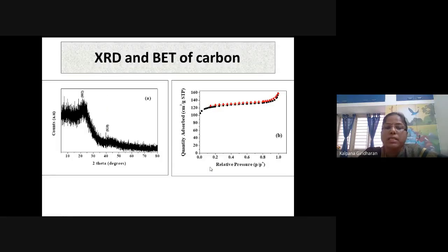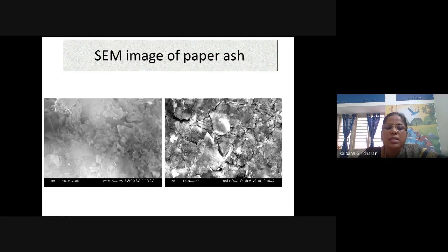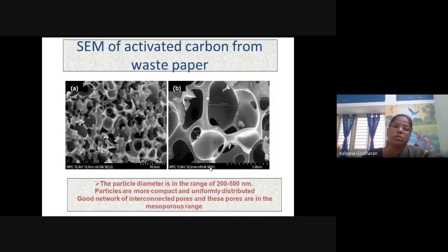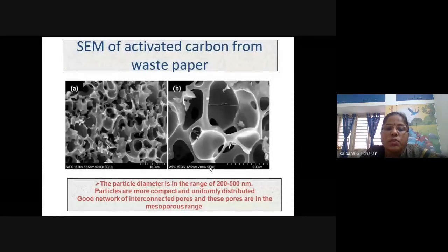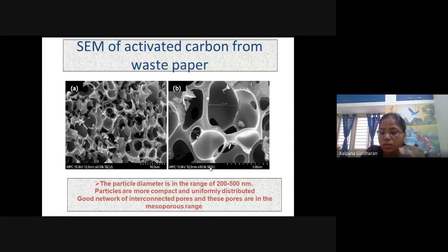And the typical XRD, and BET surface area analysis. This is the SEM of paper ash, and this is after activation. You could see the particle diameter is in the range of 200 to 500 nanometers. The particles are more compact and uniformly distributed, with a good network of interconnected pores, and these pores are in the size of nanometers.